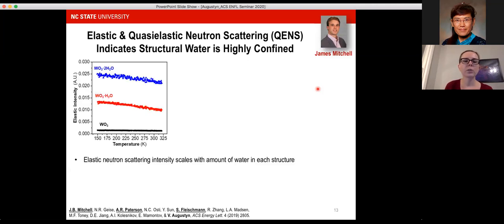And what these results told us was that the structural water in these crystalline hydrates is highly confined. The results were also useful in telling us that the elastic intensity scales with the amount of water in the structure. So our structure was correct, as we predicted.